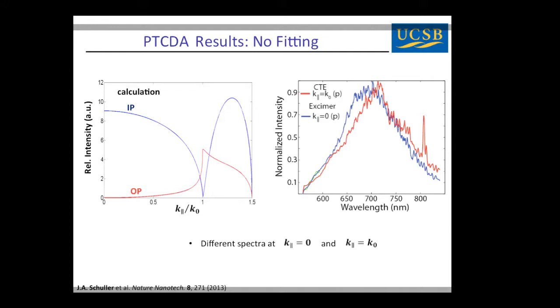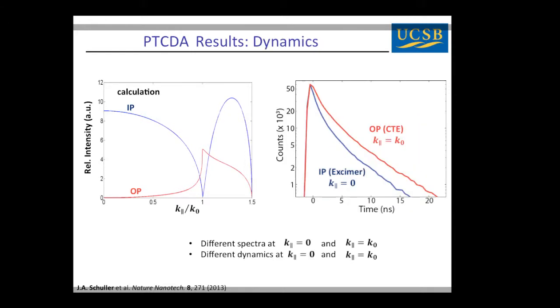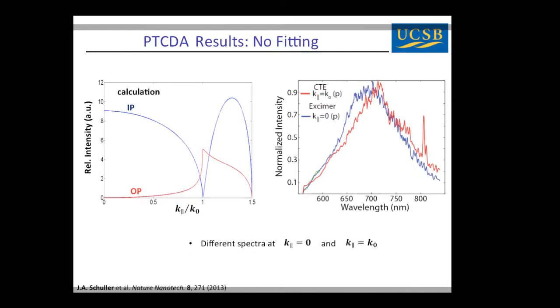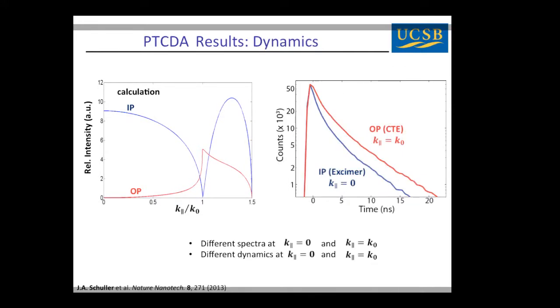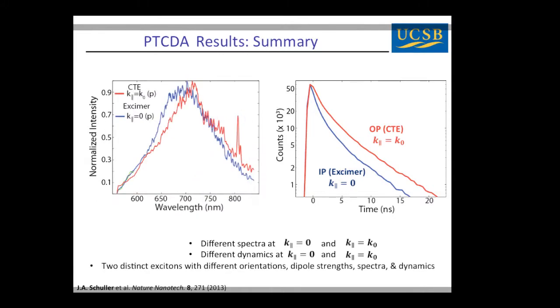Okay? And now, because we're filtering in momentum space rather than fitting in momentum space, we can not only plot the spectra, but the dynamics. Okay? And so we see different spectra, and we also see different time traces of the dynamics. And this was really the proverbial nail in the coffin that really proved to us that we have two distinct exciton species. Okay? So we have two distinct exciton species. They have different orientations. And as a result, they have different spectra as well as different dynamics.